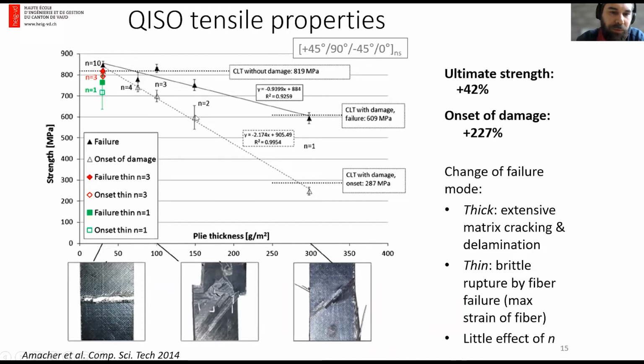While when we decrease the ply thickness, the onset of damage increases significantly. We reach 600 megapascal, which is actually the strength of the thick ply, and the failure strength also is increasing. By reducing the ply thickness, we have actually convergence of the onset of damage and the strength of the laminate, which means that there's no significant damage occurring before the final failure of the laminate.